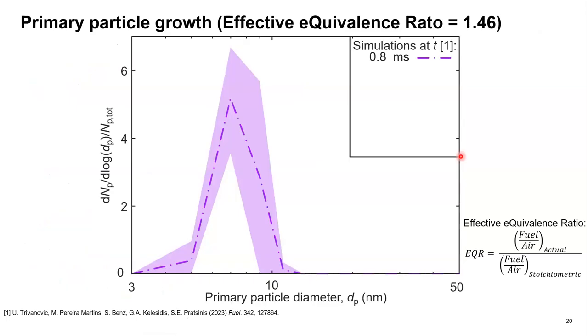Now we can zoom into how the primary particle size distributions evolve through the simulations. So on the x-axis, we have the primary particle diameter, and we have the simulations here where the line again represents the average of several different simulations, and the shaded area is the variation between those simulations. So at a simulation time of 0.8 milliseconds, we have a median primary particle diameter of about 7 nanometers. Increasing to a simulation time of 1.7 milliseconds, this shifts to the right to a median just above 10 nanometers.